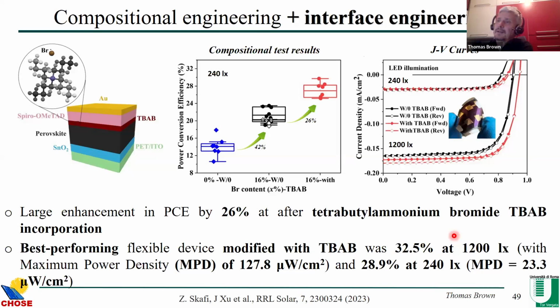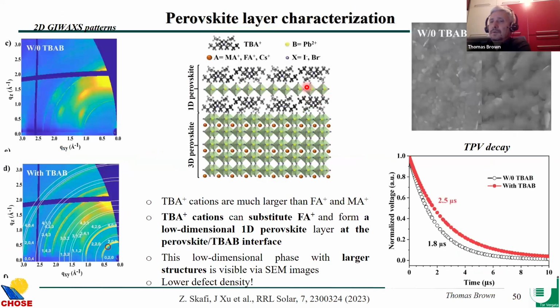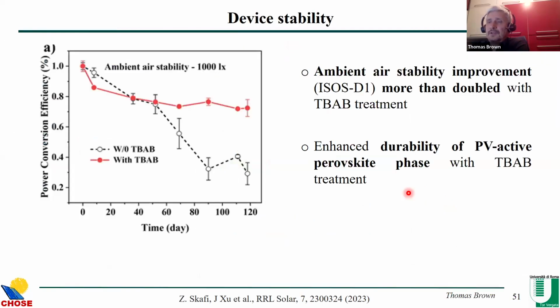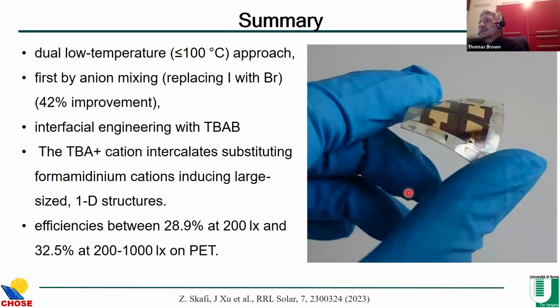So we talked about why there's a jump increasing the band gap. Why is there a further jump when you do interface engineering? Well, we teamed up with groups who carried out GIWAXS and XPS. We found that the TBAB was creating a one-dimensional perovskite here, which is more stable, leads to fewer defects. And you can see that by the transient photovoltage decay, where this time increases, leading to lower recombination probability. And actually, TBAB also increases the lifetime of the devices. So at the time, which was a year ago, these were the highest efficiency devices on PET.